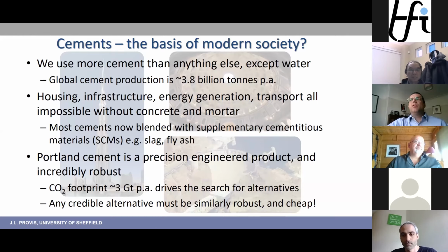Portland cement, we think of as, oh, that's a cement factory I'm driving past. That's grey, that's ugly, that's dirty, that's clearly outmoded. Portland cement is actually a precision engineered product. Portland cement as a material is an engineered combination of at least 5 different mineral phases. Sometimes you get some additional ones to go up to 6 or 7 that become important. Ground to a particle size distribution that gives the exact strength development profiles you need. The different ratios of the mineral constituents are balanced to give you what you're looking for in terms of early age properties in the fluid state and in the hardened state.